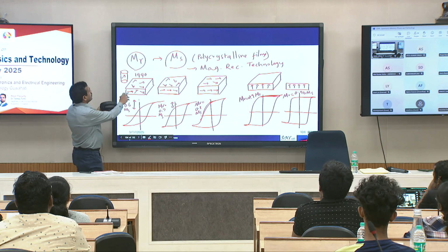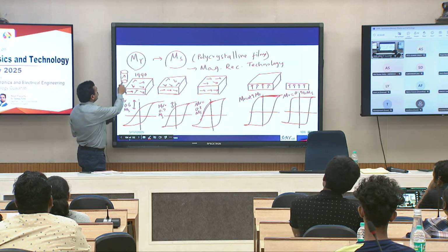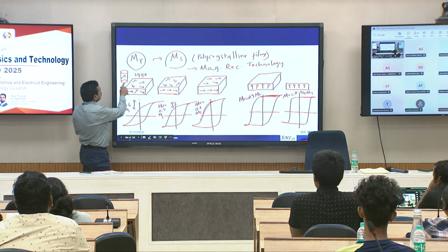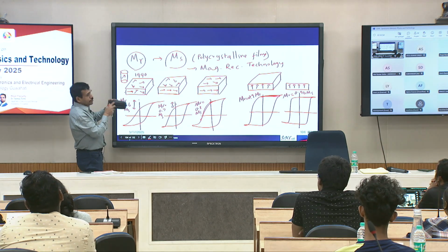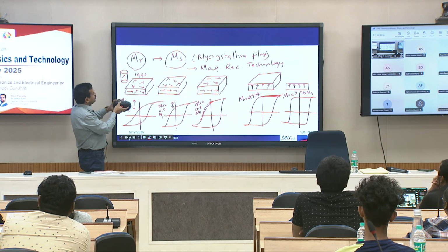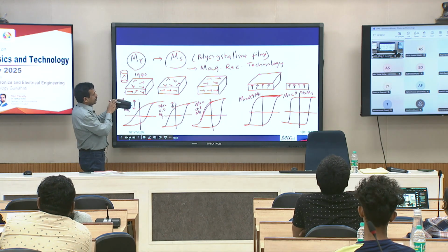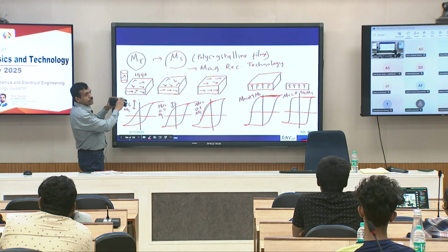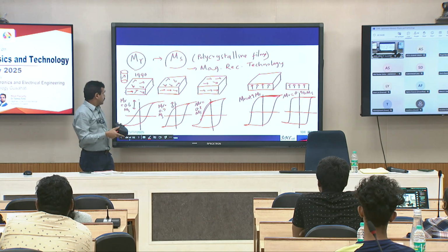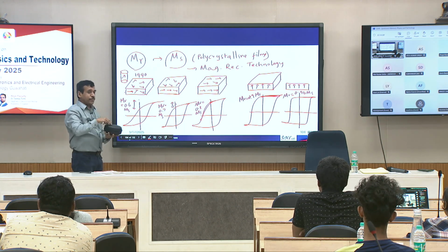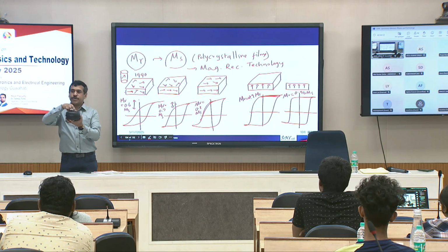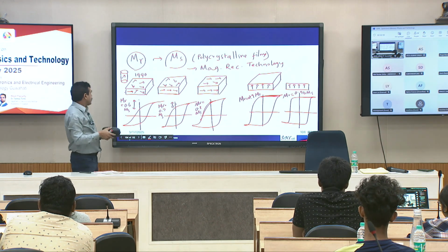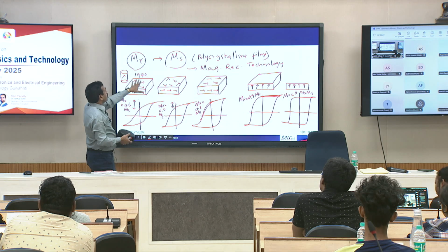In longitudinal magnetic recording, your grains may have easy direction, if you view from this perspective, completely parallel to this plane, or tilted at some angle with respect to this plane. So magnetization can be this way or like this. A few possibilities exist. And now, if you view from the top, within the plane, again the magnetization can point towards you, or towards this wall, or towards this wall. So it can point in many directions. From the top also you have randomness.